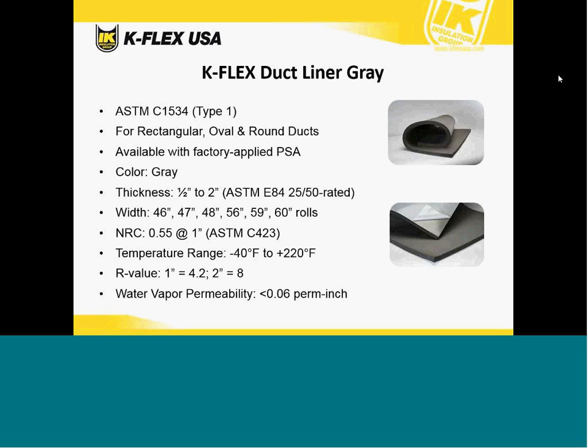Standard width product is 46, 47, 48, 56, 59, or 60-inch rolls, depending on the coil line that it will be run on. The noise reduction coefficient is 0.55 at 1 inch, as tested by ASTM C423. The temperature range for this product is from -40 Fahrenheit to +220. The R-value at 1 inch is 4.2, and at 2 inches is 8, which complies with most local codes. And the vapor permeability of this product is less than 0.06 per inch, which is below that ASHRAE Class 1 vapor retarder line.